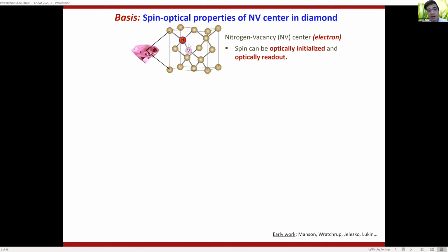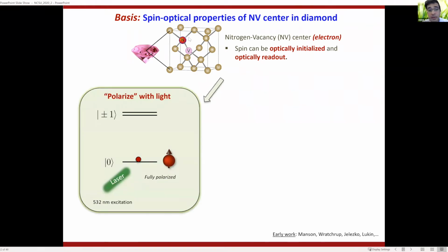So these defects are basically where you take a carbon atom, you replace it with a nitrogen atom, and you have a vacancy nearby. And they have two very special properties. One, you can polarize them. These turn out to be electrons, and they're spin 1 electrons. And that's like a generic structure of a spin 1 electron with zero magnetic field. It turns out if you shine light on these spins, you can polarize the spins with light. So you can put 100% of the spin population of this electron in a particular spin state.